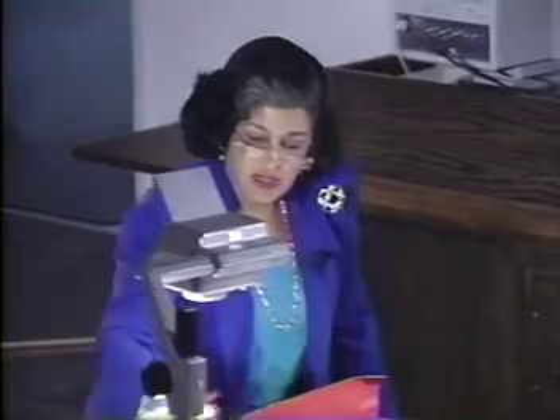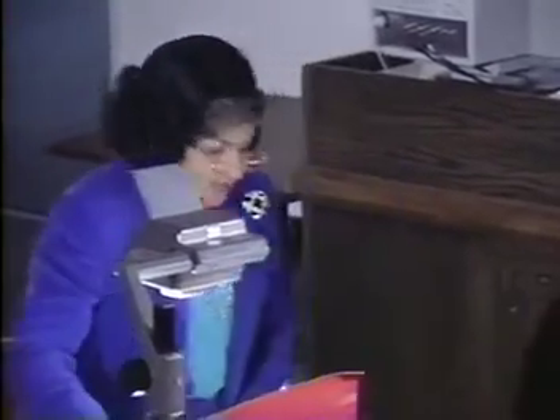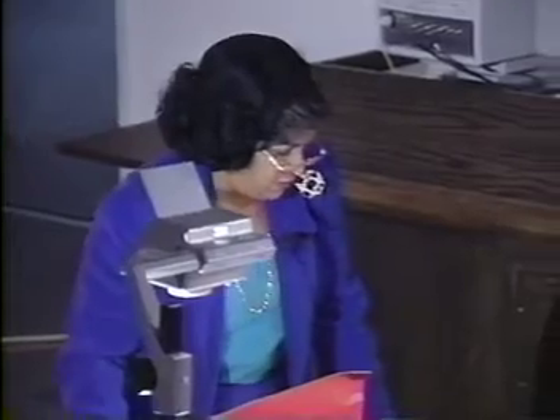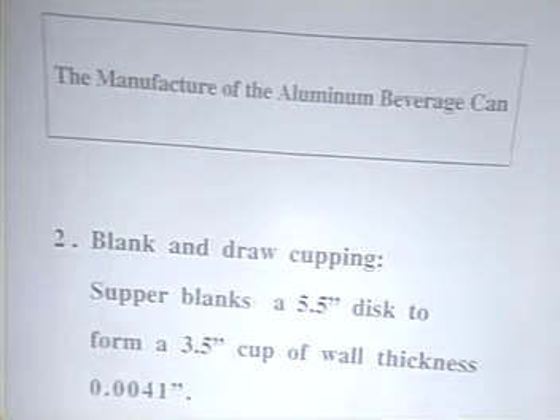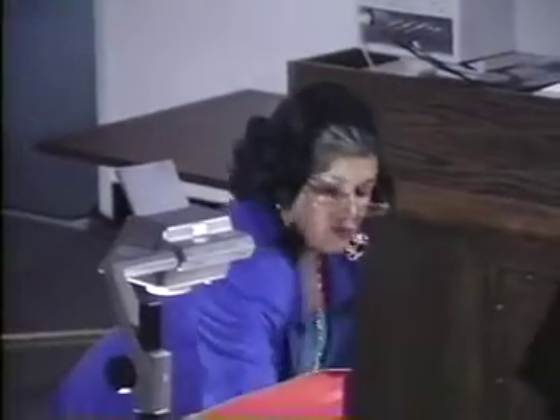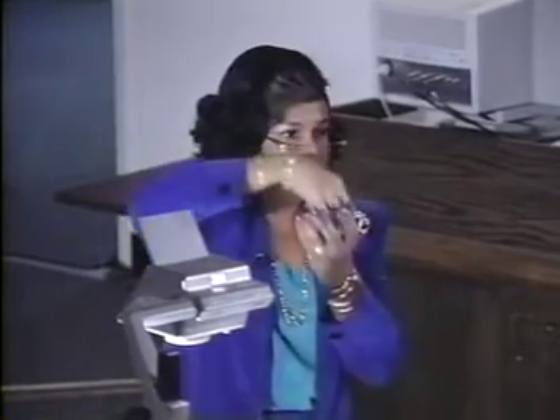So what happens then during this rolling, to get this sheet that's 0.016 inches, it's going through a series of rolling mills and getting thinner and thinner and thinner and thinner. Okay? So finally we get this sheet that's 0.016 inches, and then we start another process that we call blanking and drawing. We start out with a blank, and it just kind of like punches out a 5.5 inch disc. And then another punch, and I'll show you a picture of it in a minute, actually forms a draw cup. This is the first step. This was a flat, cylindrical 5.5 inch disc. Then a punch comes down the disc and makes it into the blank draw cup.